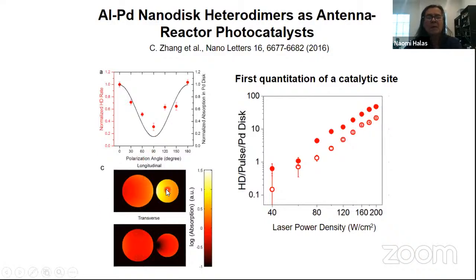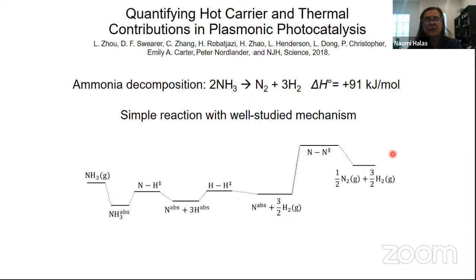And what I think is also very exciting about this is that because we've written the structure, we know exactly how many catalysts we've written on the structure. So we can actually quantify how much hydrogen is dissociated per laser pulse per catalyst, right? In a normal case of catalyst, you're not counting the number of catalytic sites. That's impossible. But here we now have a system where you actually can quantify absolutely every aspect of doing a chemical reaction. So we think this is a really exciting and special way to think about doing chemistry now and in the future.